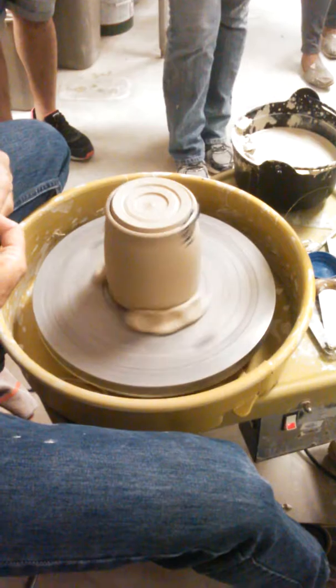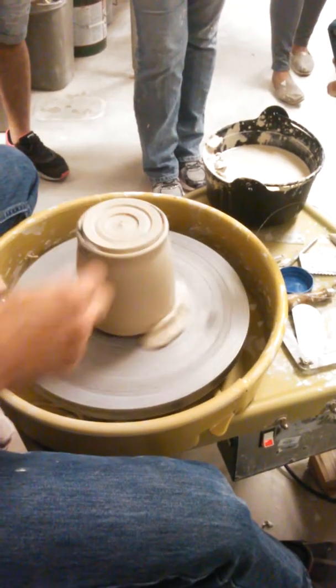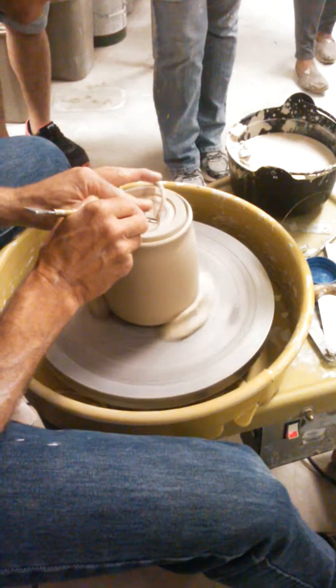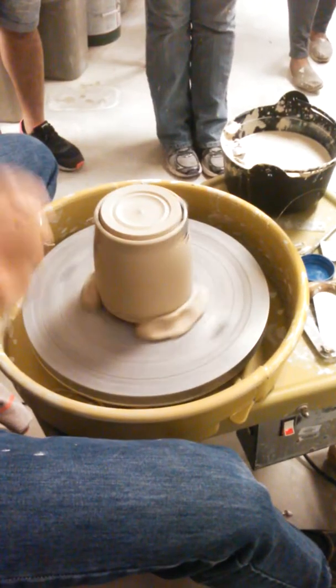That's a good question. There are two waxes: the regular wax and then the wax that says 'wax with alumina.' I always use the wax with alumina for any lids. Alumina is a very refractory material and it acts like ball bearings in there — keeps the lid from sticking.